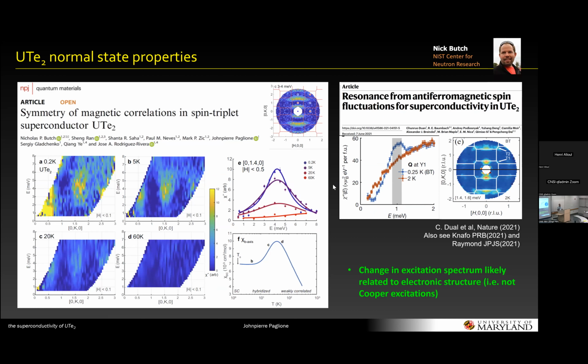Okay, so I'm going through all the controversies. Neutron scattering, there's been several inelastic neutron scattering experiments. I would say, roughly speaking, they all agree. They all give you a picture that's sort of in this top corner here, where there's intensity along the Brillouin zone boundary along the B-axis. And it's an incommensurate Q vector. And so this has been interpreted in different ways.